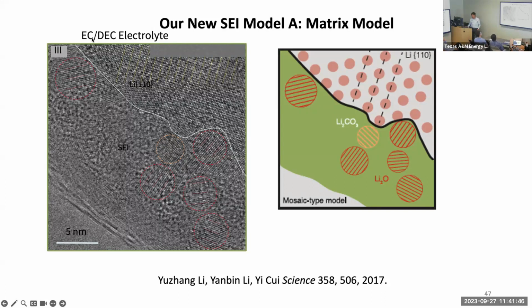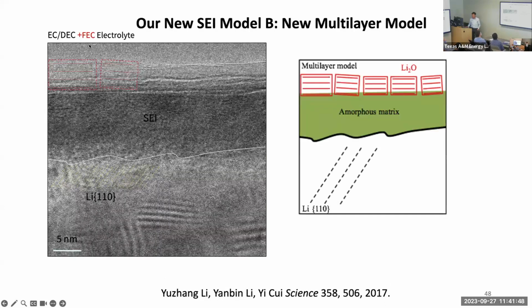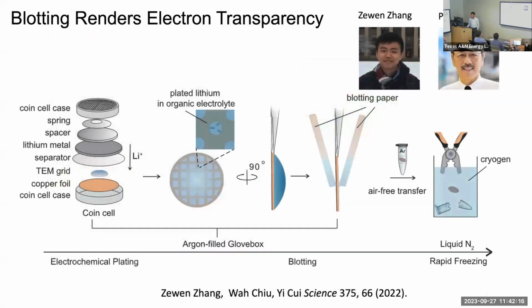This is in a carbonate electrolyte. As soon as you add a little bit of fluorinated FEC, this whole structure changes. Now you have this beautiful layer on the top that's all lithium oxide, then you have this amorphous layer, so you have a bilayer structure. This actually resolved one of the disputes in the field for the past 30 years, called the mosaic structure or bilayer structure. It turned out both exist, depending on your electrolyte. So we resolved that.